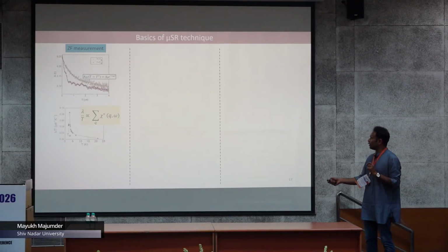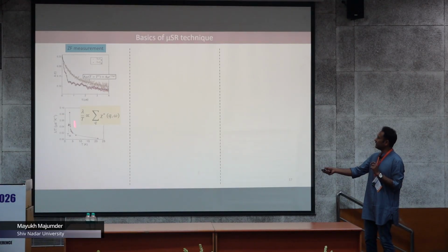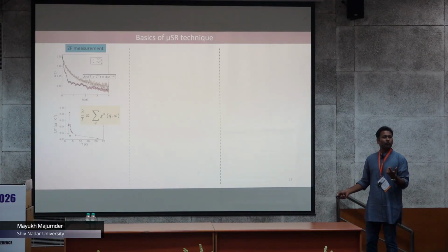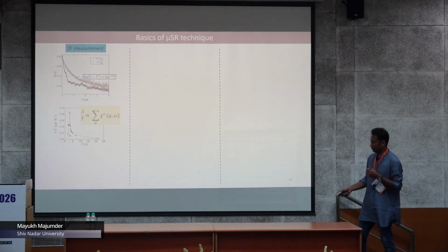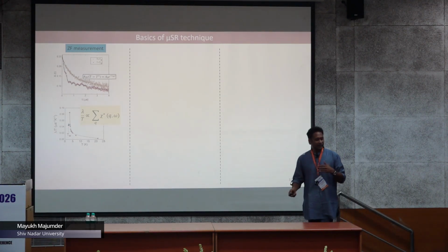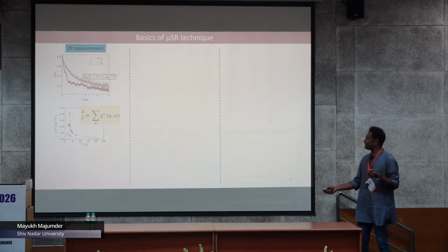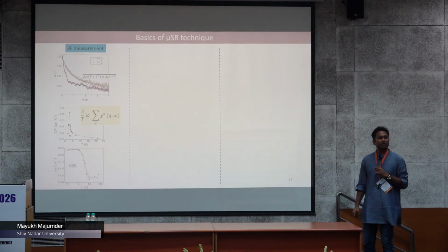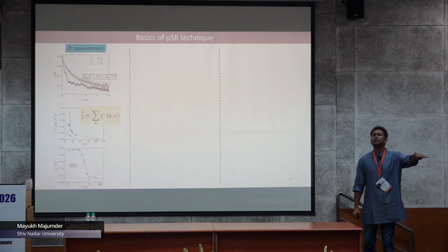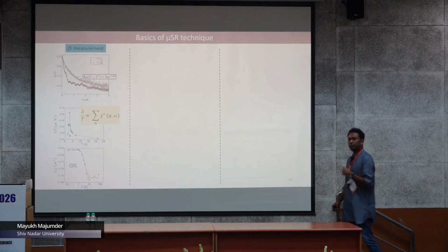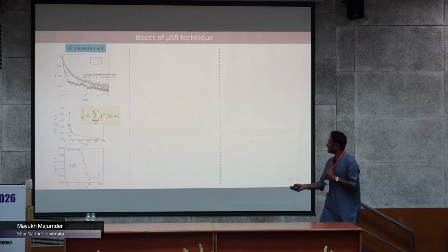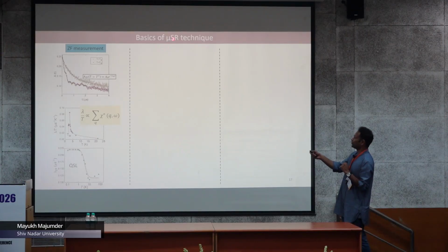Okay, so now if you have a long range magnetic ordering, you would see some peak in lambda as a function of temperature. But if you are dealing with, let's say, a quantum spin liquid, then instead of a peak, you would see a temperature independent lambda, indicating you have persistent spin dynamics. Okay, so there are actually 3 protocols associated with muSR.